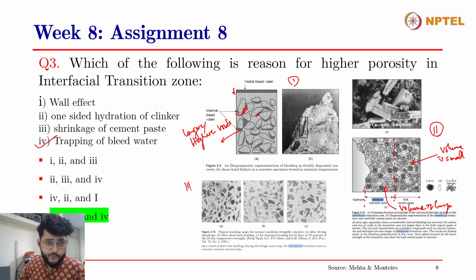The third view graph shows you typical cracking maps around this. This is an SEM micrograph, and you can see that around the aggregates there are micro cracks present at the ITZ. This is due to, again, as we have discussed, shrinkage of the cement paste. When the cement paste hydrates, it undergoes chemical shrinkage. So if I draw a rough aggregate, and here is the ITZ, and here are the cement grains.